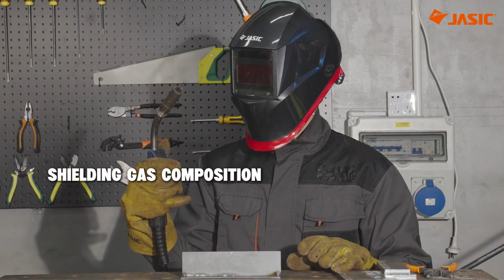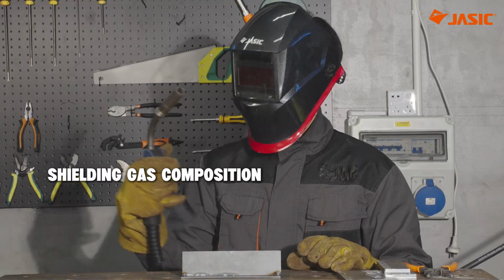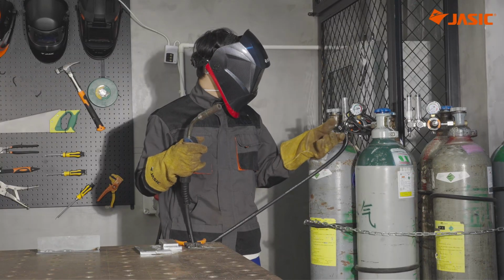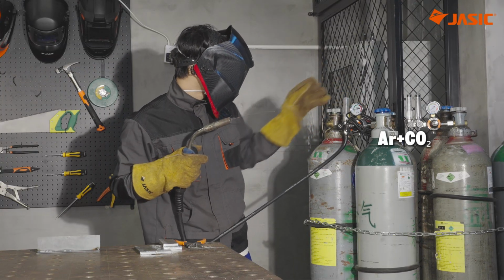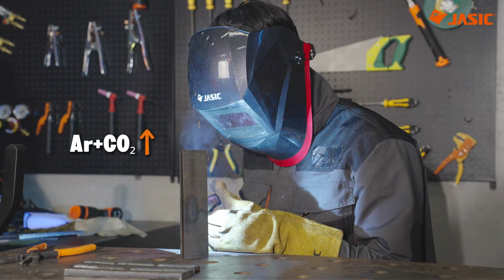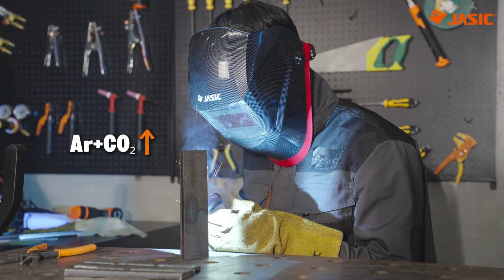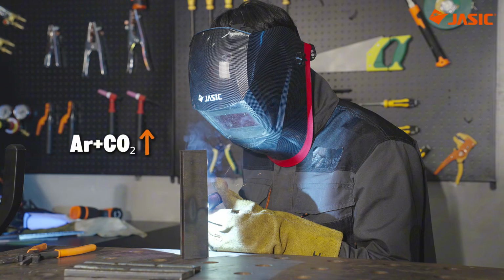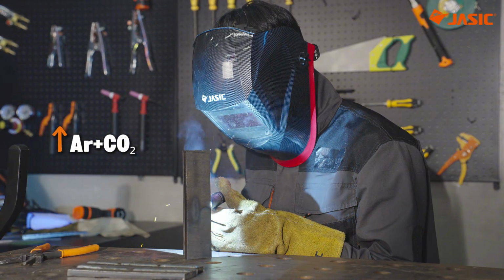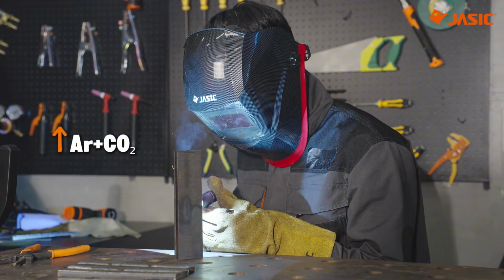First, shielding gas composition has a direct and significant effect on spatter. In MIG welding, the most common shielding gas is a mixture of argon and carbon dioxide. The more carbon dioxide in the mix, the more oxidizing the gas becomes, making the arc less stable and increasing spatter. A higher percentage of argon produces a smoother, more stable arc with much less spatter.